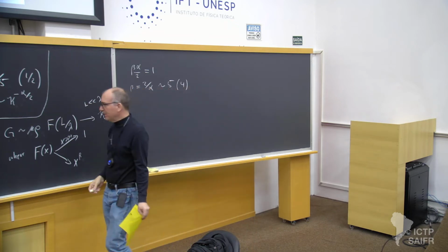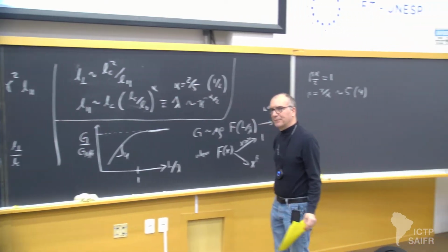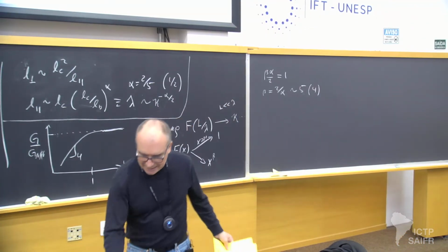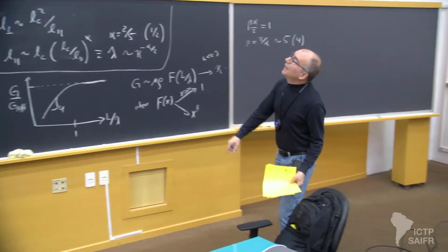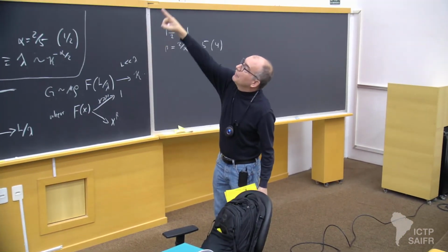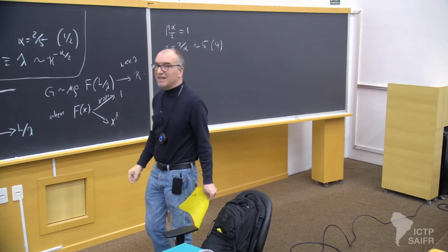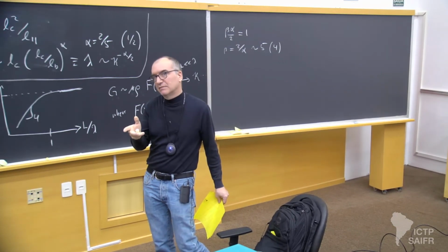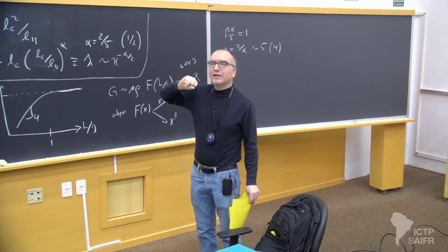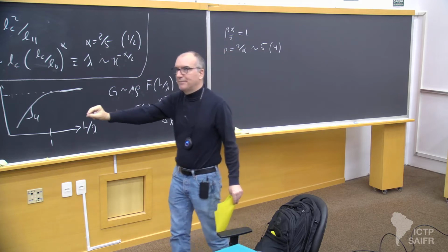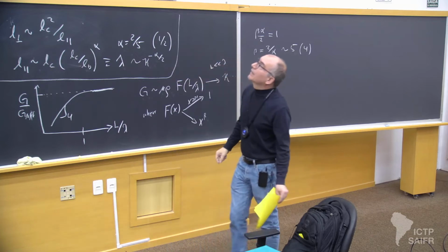But the point is it's a big power. So this winds up being 4. Does that work? Well, sure enough, you can put a line on this log-log plot for that range there, and you'd see an exponent of about 5, okay? It happens those data are not really in the asymptotic regime just yet, and so it's apparently about 5, but not exact.